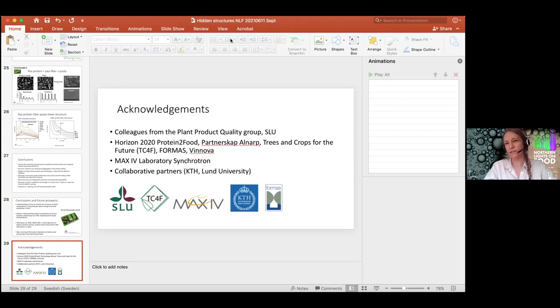Yeah, that was also talked about, I think, in Milena's talk and in several other talks, that, for instance, spray drying is a very harsh processing method, and you never get the protein in native form. So you simply introduce changes, and that's what we explored in the lab. To work with gluten is rather easy because you can easily wash it by hand from flour. You simply make a dough, and then you wash under the water, and then we analyzed that structure and compared with industrially produced gluten, and we saw much more native properties in the gluten produced in the lab, meaning that proteins are more prone to interact and form polymers.